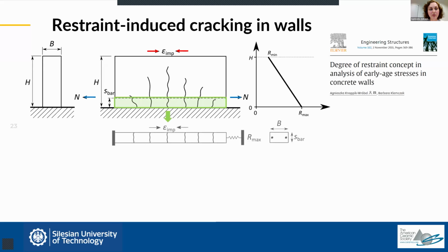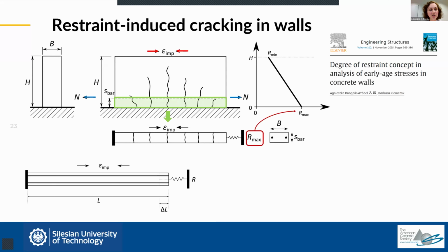So what we do is we cut a portion of the wall and we represent the portion of the wall as a tie, which means an element which is subject to axial tension. Nonetheless, this tie is not fully fixed, but it is only partially restrained. And the degree of this restraint that we use in this simplified model relates to the maximum degree of restraint because this is where we expect the maximum crack. So our design model would actually look like that.